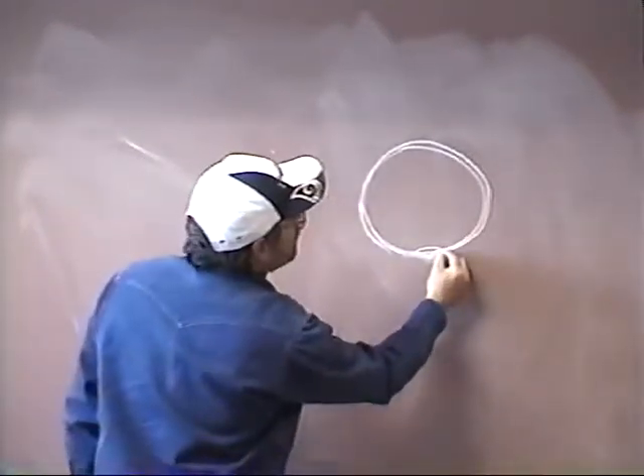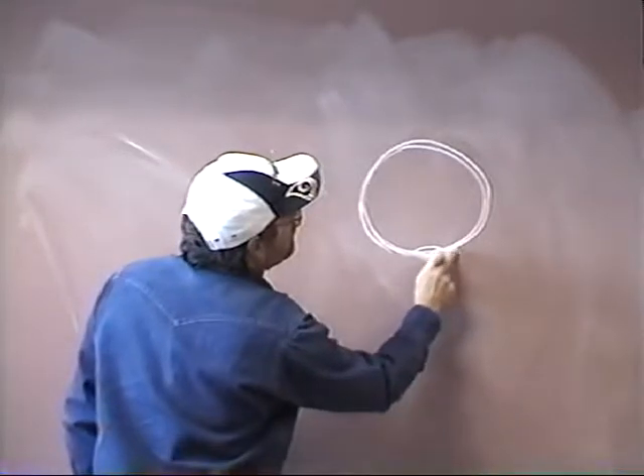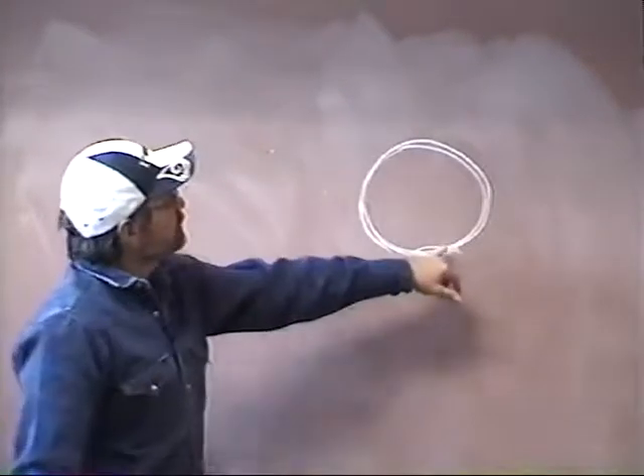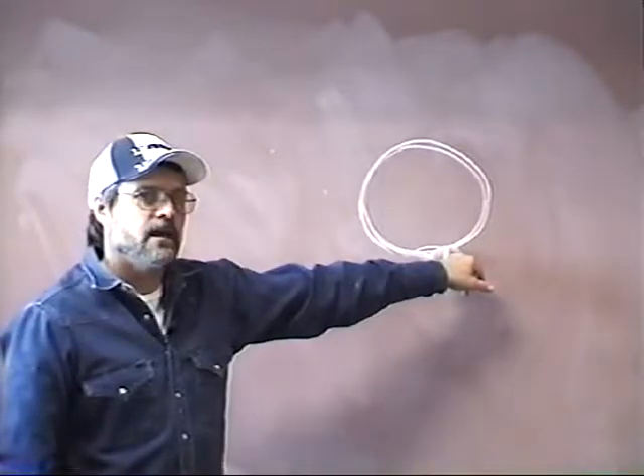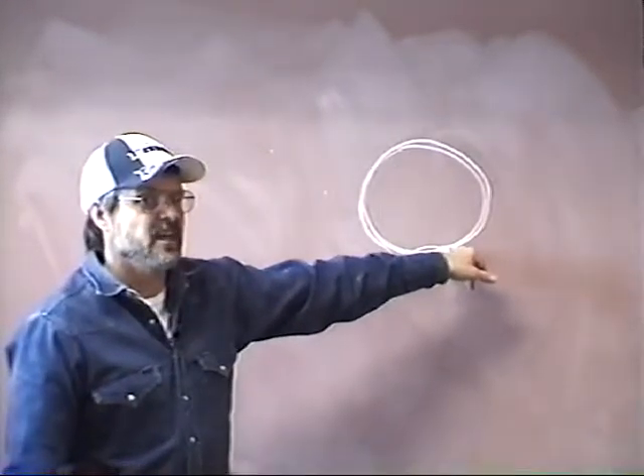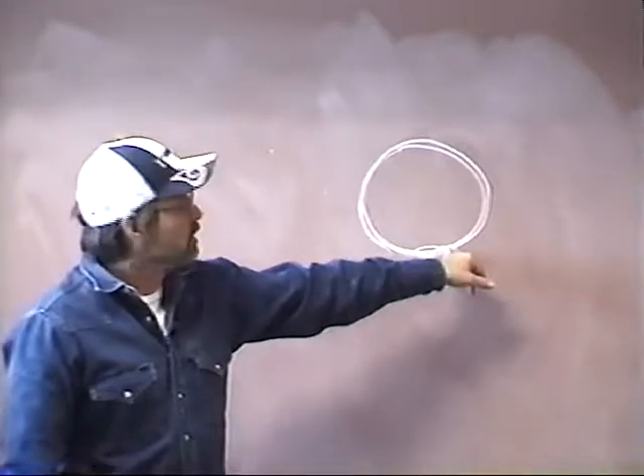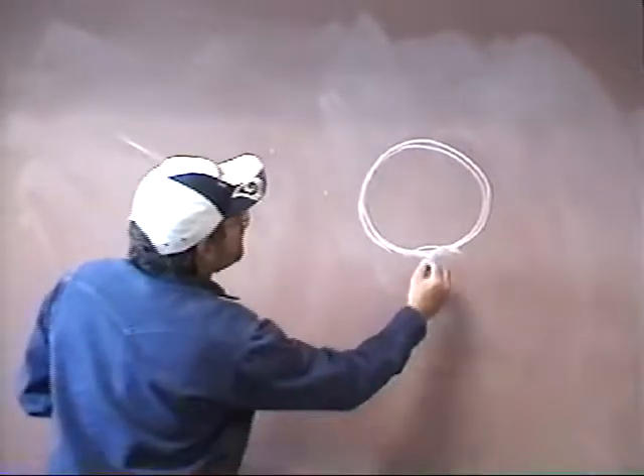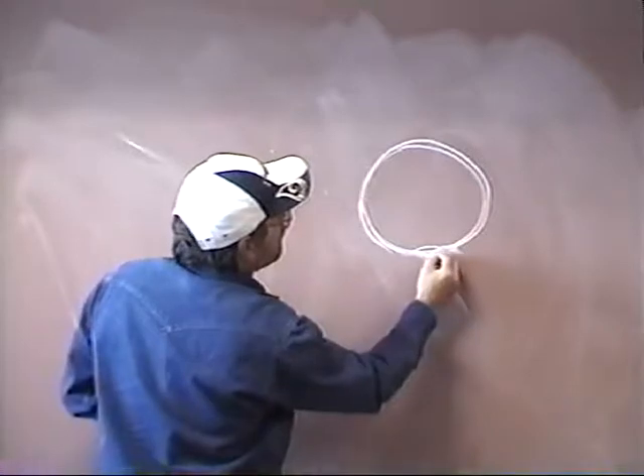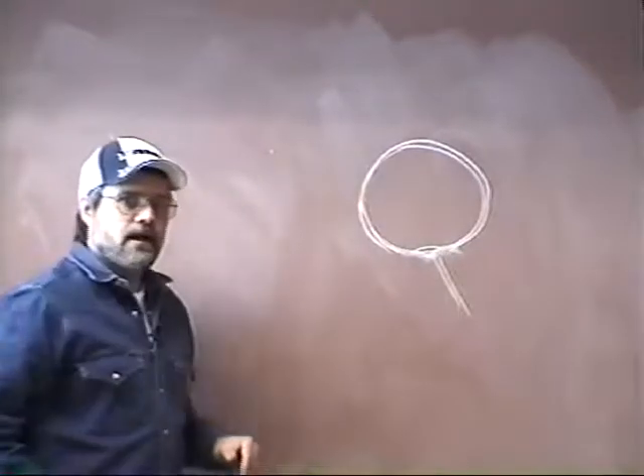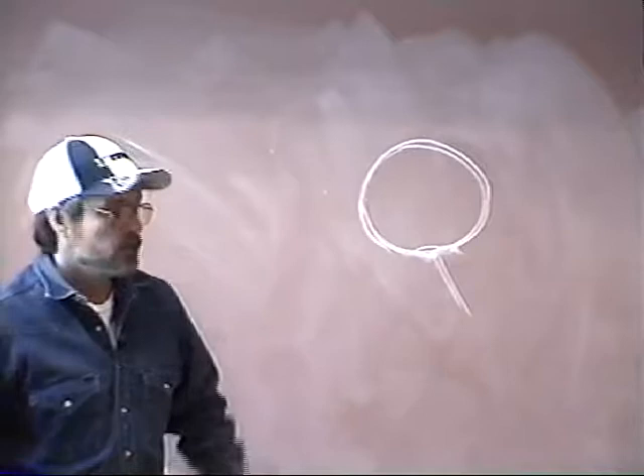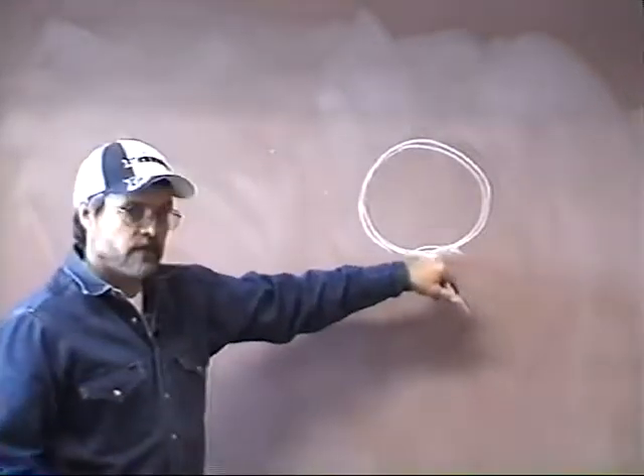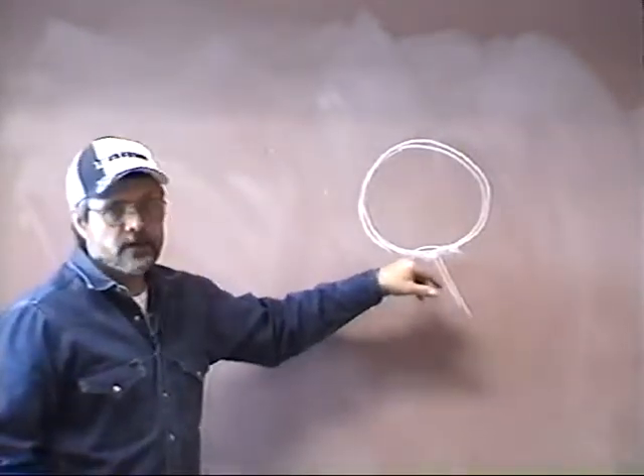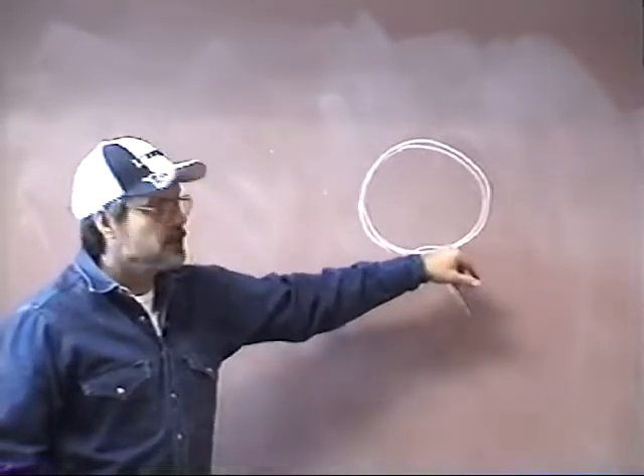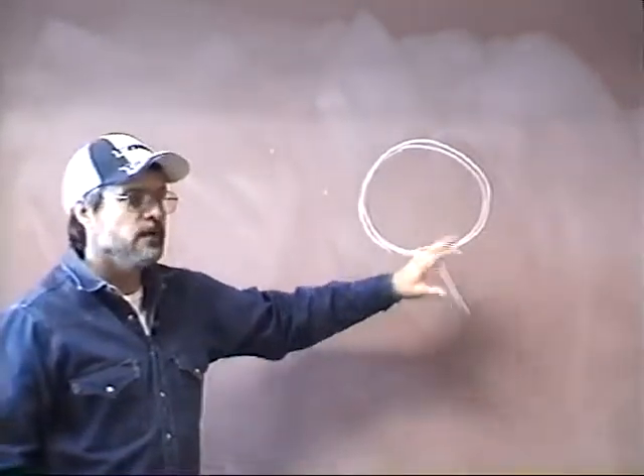But you weren't careful. You ground past the end of the tack, and you got out there and you removed some of the thickness of that land. So instead of having a 3/32 land here at the end of your tack, you've only got a 32nd of an inch land. So there's no meat there to hold the heat. So when you come welding out of there with your stick, suddenly you hit that really thin spot of land, blow a big hole in it. So it's very important that whenever you prepare these tacks, whenever you grind them, do not grind past the end of the tack. Don't remove the meat of that land. You got to leave that in there to control the heat.